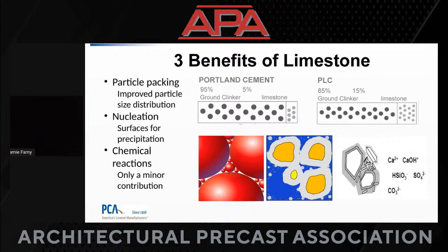So this smaller limestone particle provides another location for that gel to start growing. It's like a little anchor that we can start growing gel around. So it surfaces for precipitation, for this cement gel to grow and strengthen that matrix and develop strength. The third part of why limestone is really such a good thing to add to Portland cement is that we get a little bit of reactivity when we grind our limestone so fine like this.